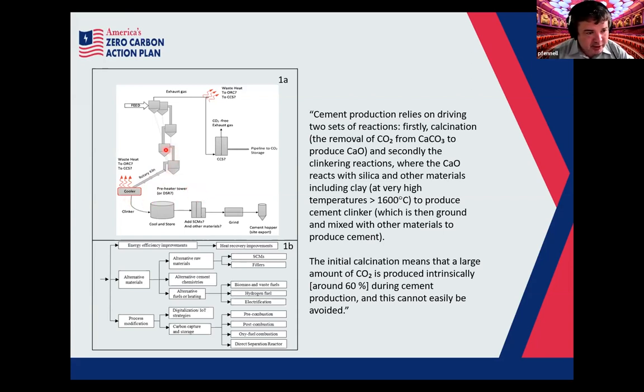There's a countercurrent flow of the hot gases from the kiln. The air comes in here and goes up, contacting the limestone countercurrently as it's coming in, and that helps to do the initial calcination, the initial reaction of limestone that pushes the CO2 off. Your exhaust gas comes out here, and you would be adding CCS on here. There are various sources of heat within the system, and heat, as I said before, is very important. I'm going to go into that in a little more detail later.